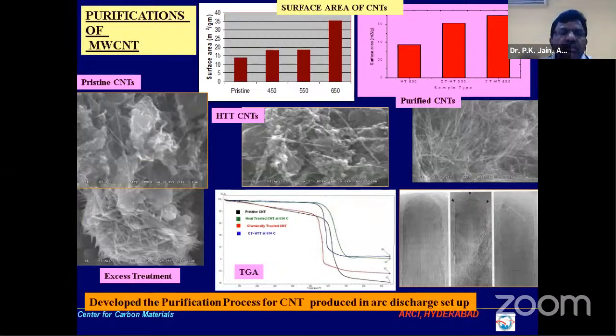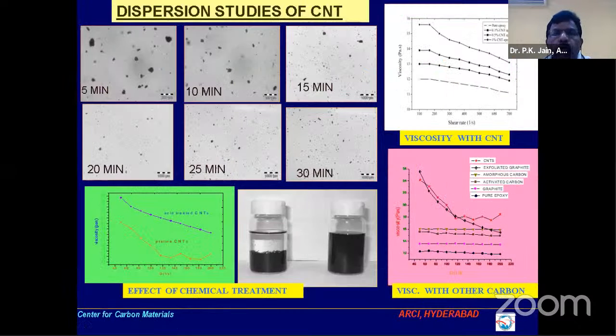Now in arc discharge, the nanotubes we get are not fully purified. They have to be purified by a heat treatment or chemical treatment, but it has to be done in a controlled way. Otherwise, excessive chemical treatment can damage the nanotubes, or excessive heat treatment can oxidize the nanotubes. So you have to optimize it. Once you optimize it, you will get purified nanotubes, and that can be analyzed through TGA, SEM and TEM.